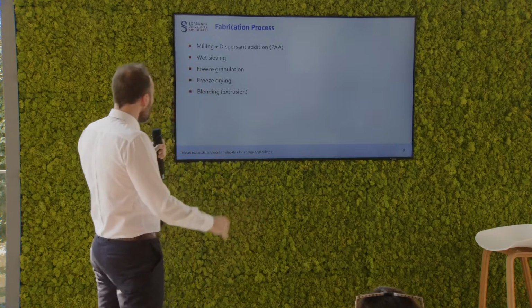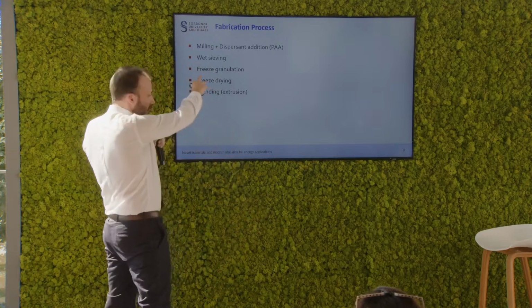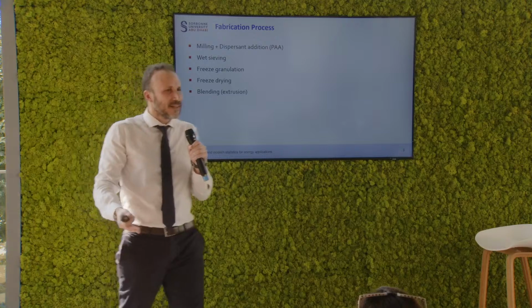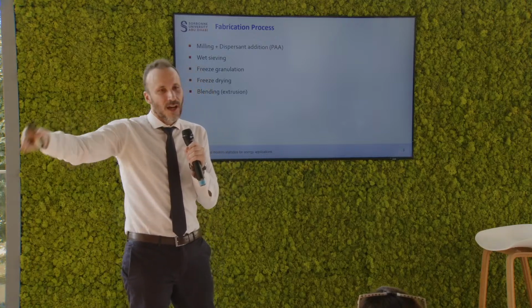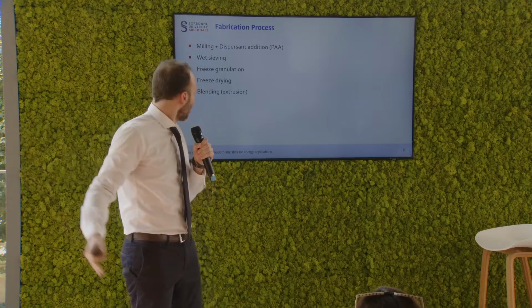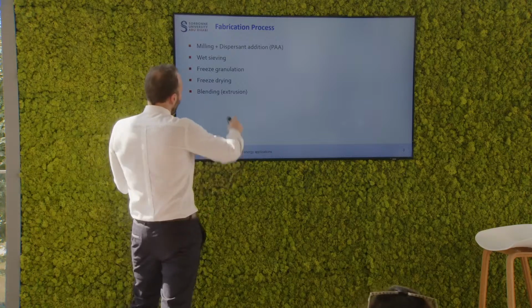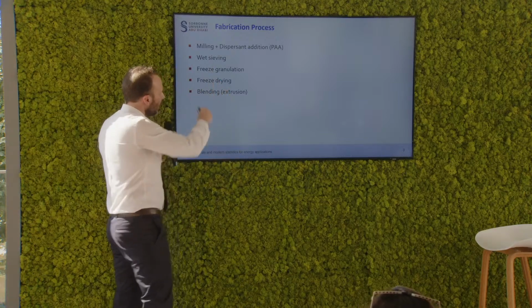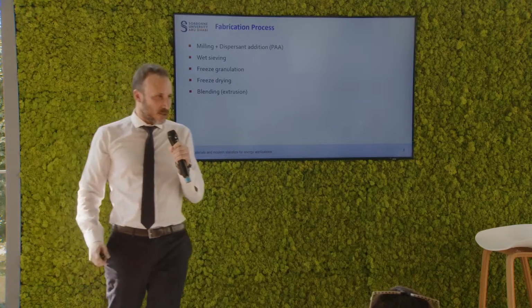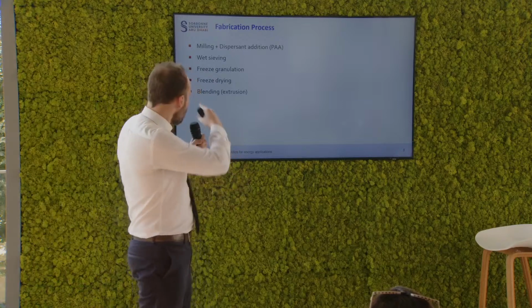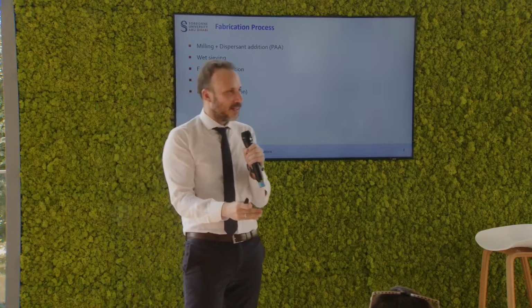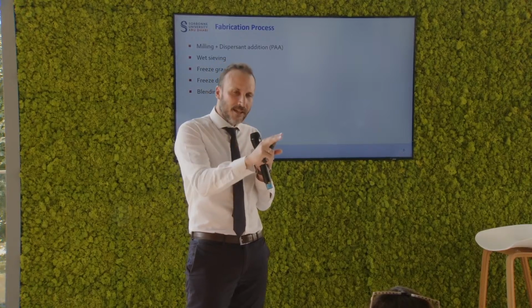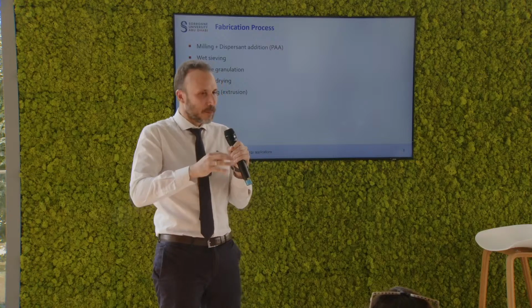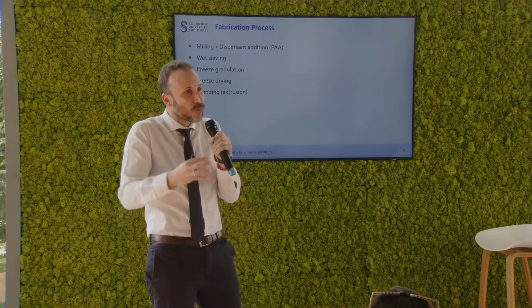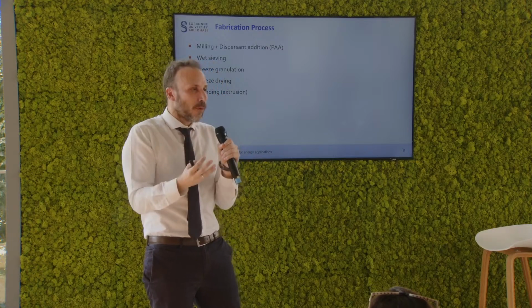So what we do afterwards is pass them through a simple wet sieving process, which is effectively there to remove the biggest of the agglomerates that we have created. The twist that we add in the fabrication process here is the third step, which is called freeze granulation. So we get these wet sieved suspensions that we have created, and what we do is inject them with liquid nitrogen. So we freeze them and we create like big chunks of agglomerates of nanoparticles.